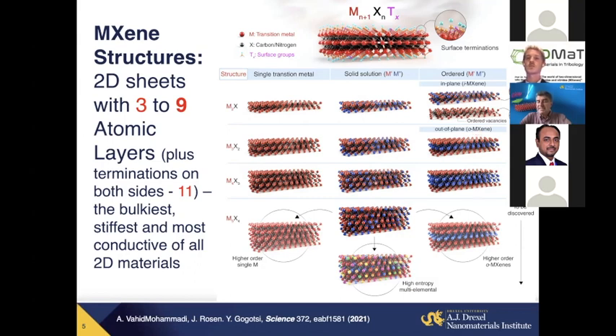It's also possible to make MXene with in-plane ordering, where there are alternating atomic columns of different elements on the surface, or to make a material with divacancies, so basically atomic columns missing on the surface. And it's also possible to mix elements. We can make a solid solution on the M side, for example mixed elements, vanadium and titanium. Or we can also make a material with a solid solution on the X side, carbonitride. And just a few months ago, a couple of papers were published on forming high-entropy multi-elemental MXenes.